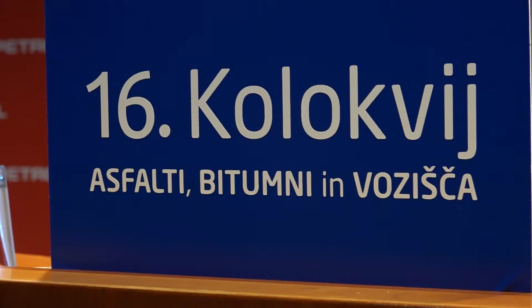It's applicable for any binders, even if you don't know the binder. You don't have to check the linear viscoelastic range before testing it. That is a big advantage. You can immediately apply this test method. And the test results are extremely robust. The repeatability is excellent. The T-BTSV is binder hardness, and it's a surrogate for the softening ring and ball temperature, especially for the plain binders. And the phase angle gives information on the degree of modification. This BTSV can be applied for binder type characterization, for quantifying aging effects in the future maybe, and for blending of fresh and extracted RAP binders.